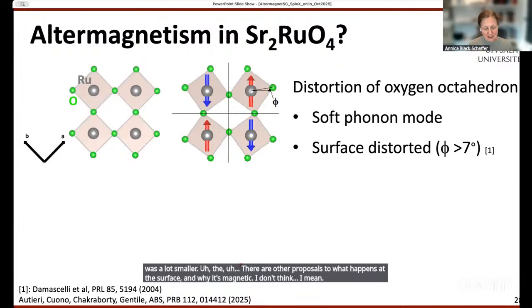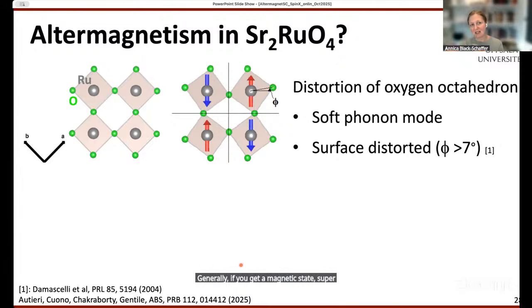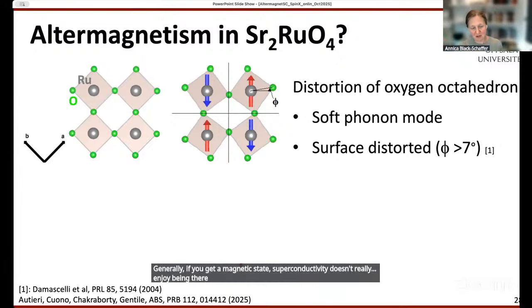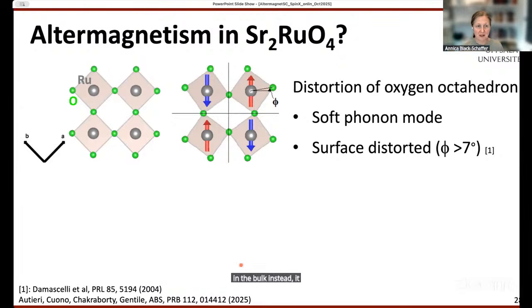Generally, if you get a magnetic state, superconductivity doesn't really enjoy being there. We saw it in the U dependence: you crank up the altermagnet strength too much, you lose superconductivity. So it's not surprising to me that you would get a surface that has some sort of magnetic state and is not superconducting, and the superconductor lives in the bulk instead. It's sort of competing phases.